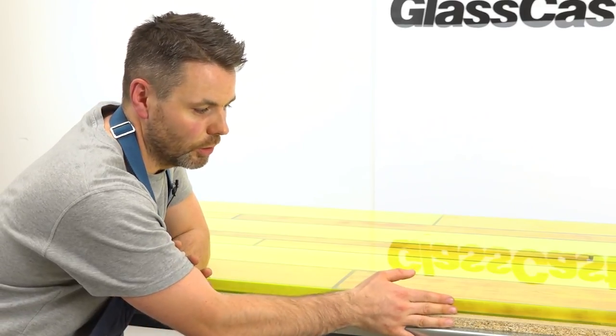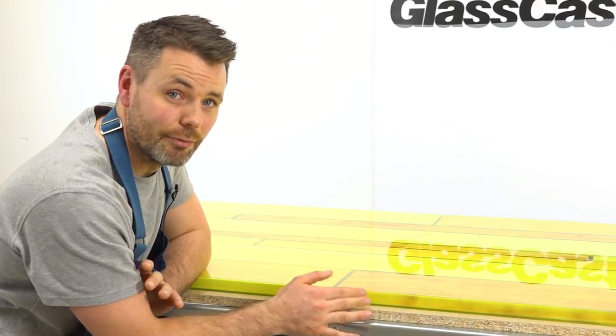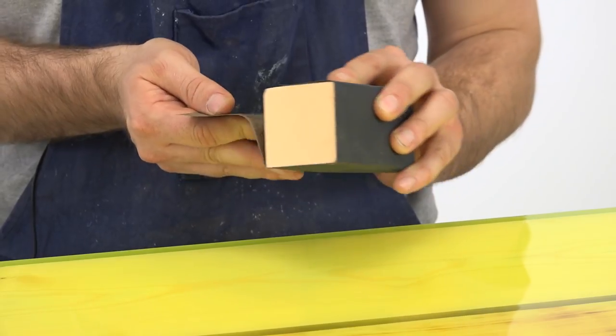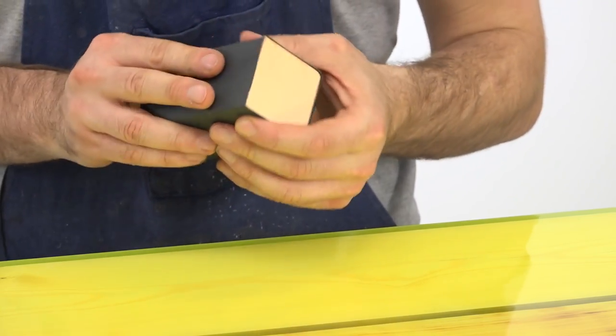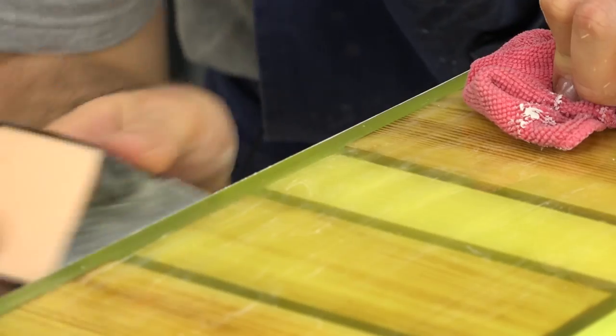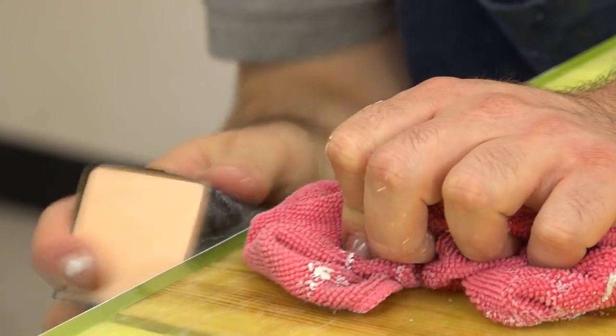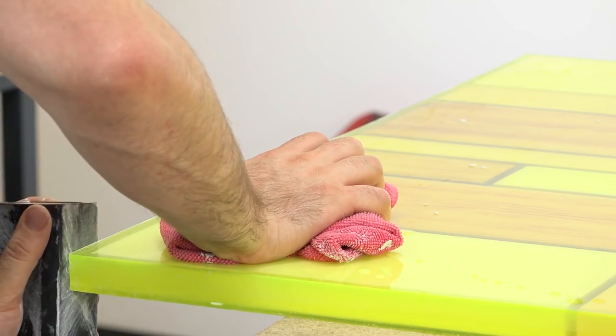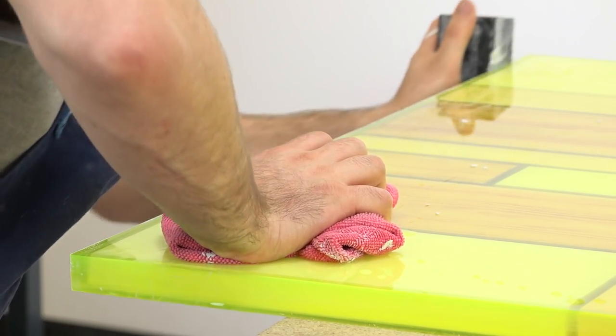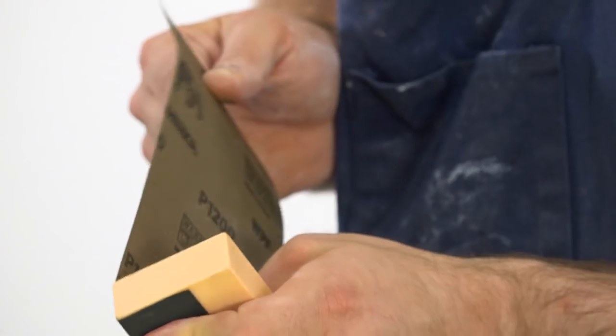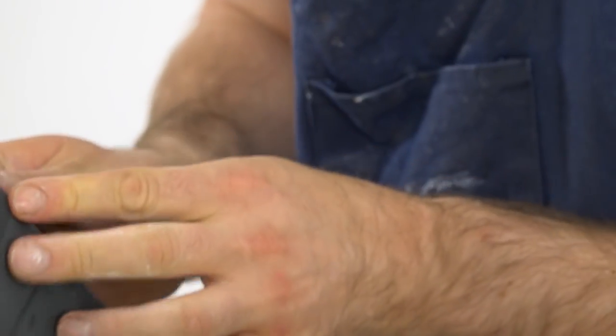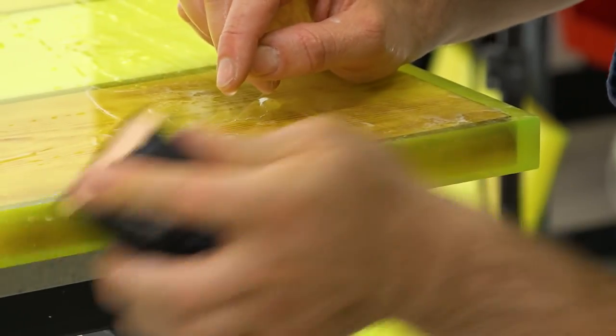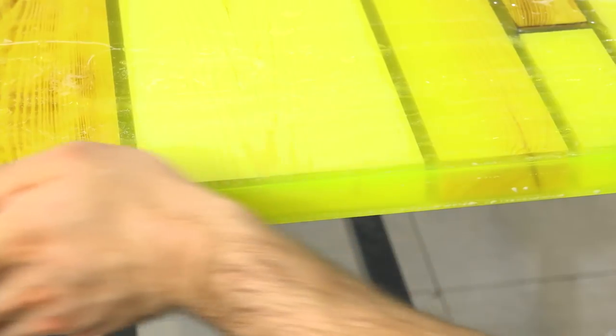This is the finish straight off the planer, and as you can see, it's actually pretty good. But to finish it to a full gloss, we're going to wet sand it and then finish with a polishing compound. Good technique is called for when flatting and polishing resin like this. You need to work up gradually through increasingly fine grits of paper. I've started with a 240 grit paper, then a 400, an 800, and finally 1200 grit.